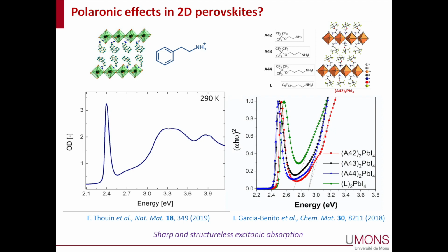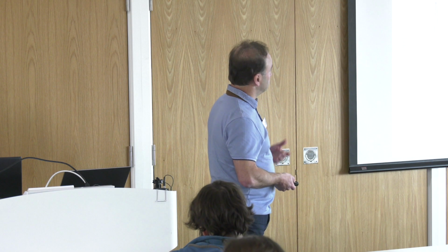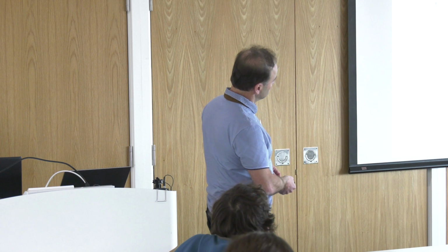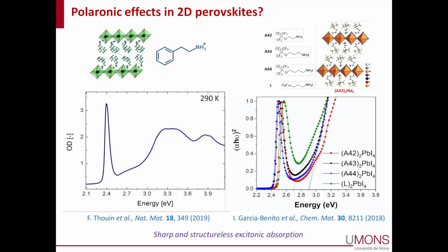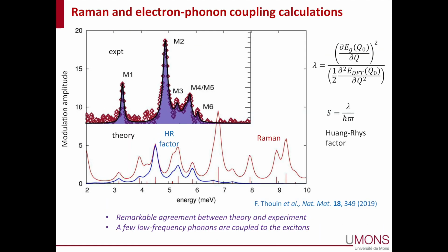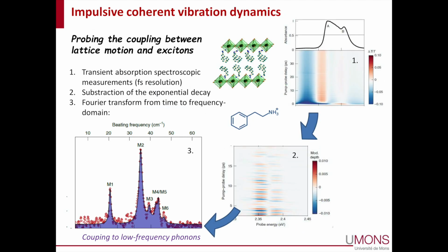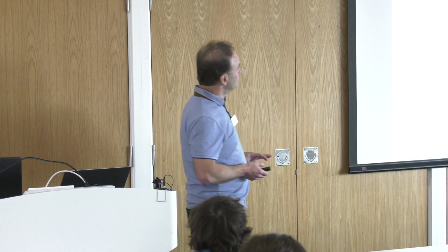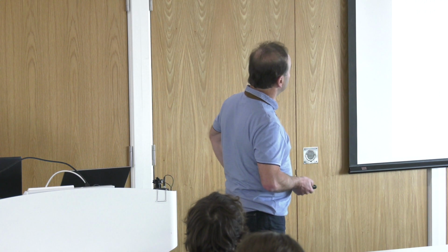But if you look at the optical absorption of a number of these two-dimensional systems, you see this very nice, sharp excitonic absorption that is shifted from the edge of the band gap absorption by the exciton binding energy, which is substantial, half an eV or so in those materials. And they are featureless. I mean, they are sharp and featureless. Really, to get a handle on or to be able to resolve a possible structure, you need to go to low temperature and use some specific techniques like transient spectroscopy.